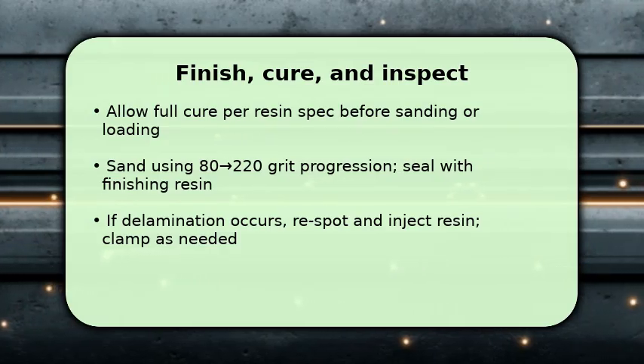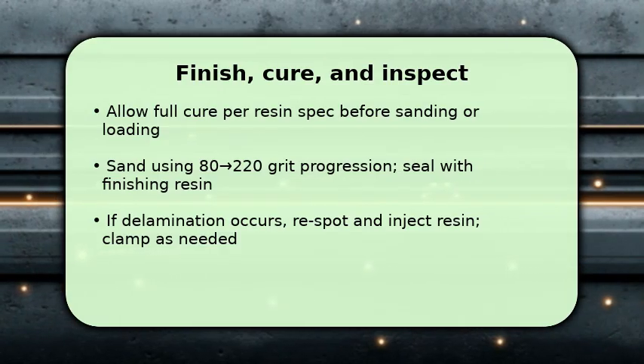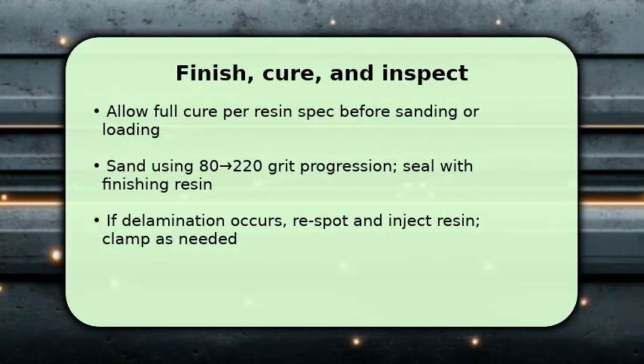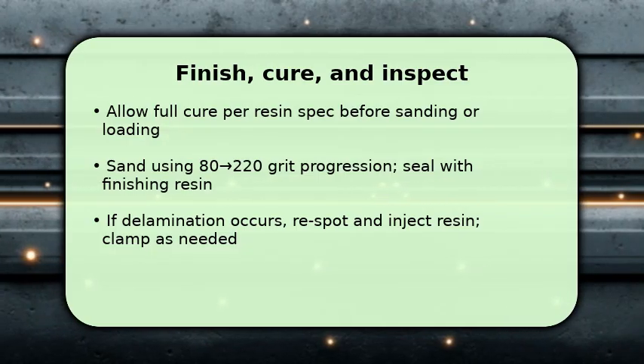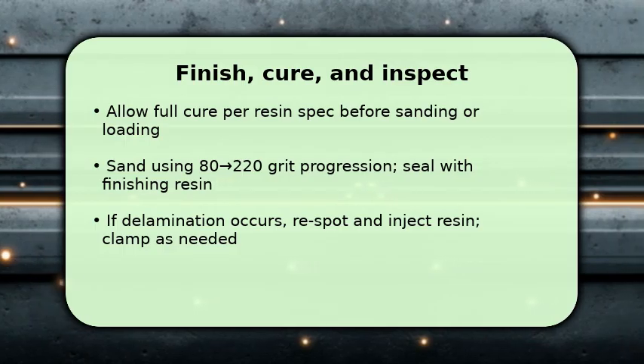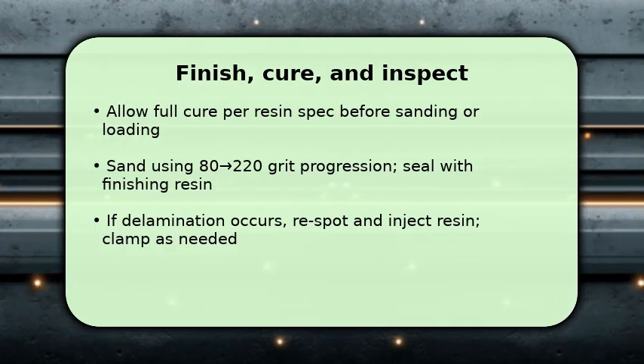If you find separation, drill a small vent, inject mixed resin into the plane, and clamp until cured. Troubleshoot by checking mix ratio and working temperature. Those are the usual causes.